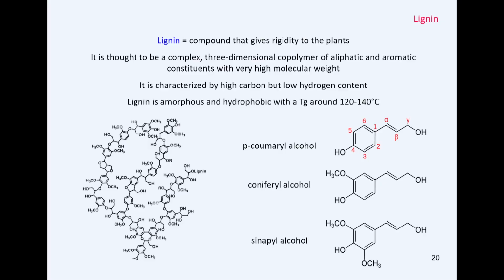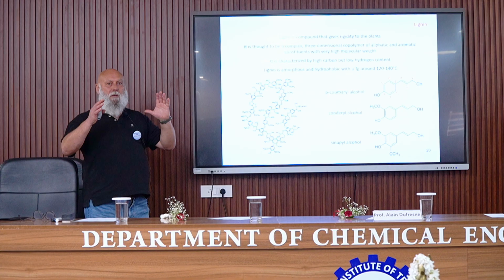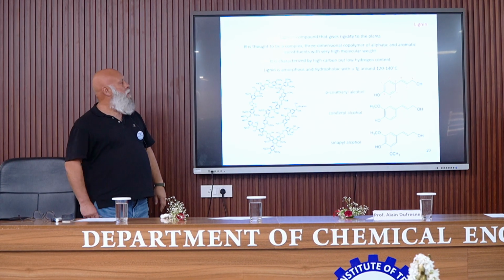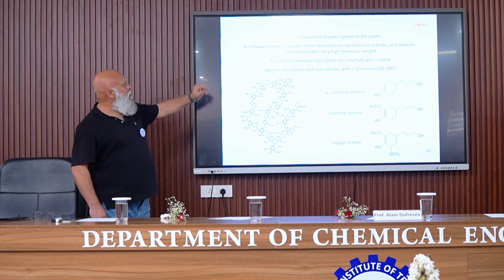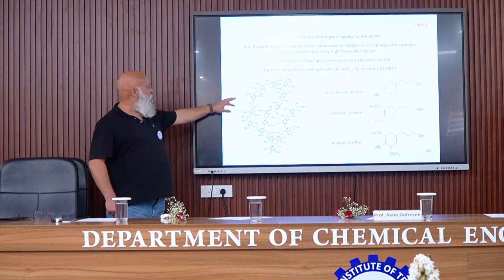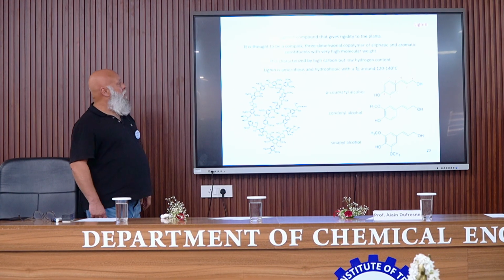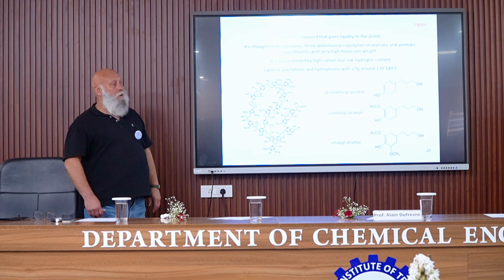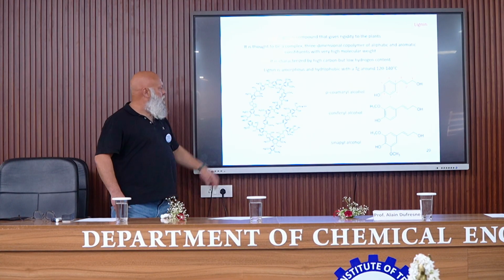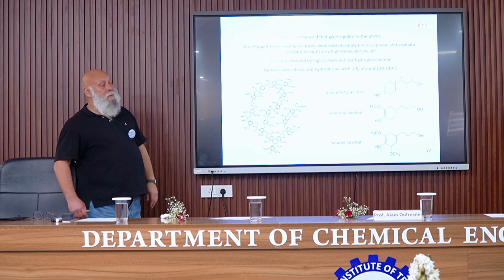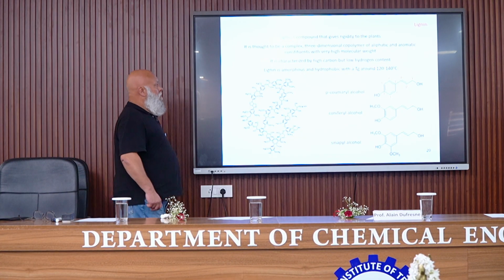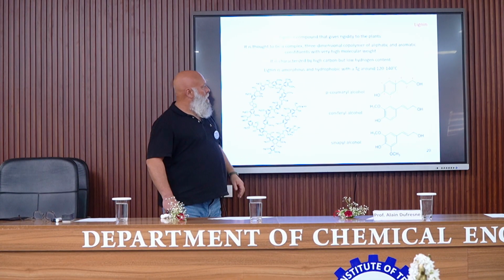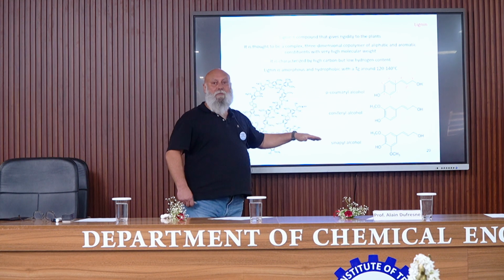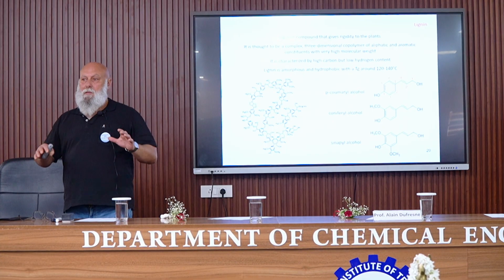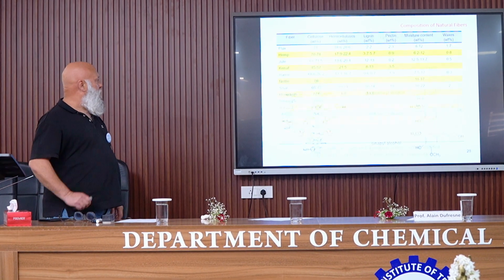And the third important component is lignin. This is a compound that gives the stiffness or the rigidity to the plants because it links or brings together the cellulose fibrils. It's a complex three-dimensional copolymer of aliphatic and aromatic constituents, as you can see here. The molecular weight is very high. The carbon content is also high, and the hydrogen content is low because of this aromatic structure. So it's an amorphous polymer. It is hydrophobic, and the Tg, the glass transition temperature, is around 130 degrees. So lignin mainly consists of these three components, made from these three chemical groups.